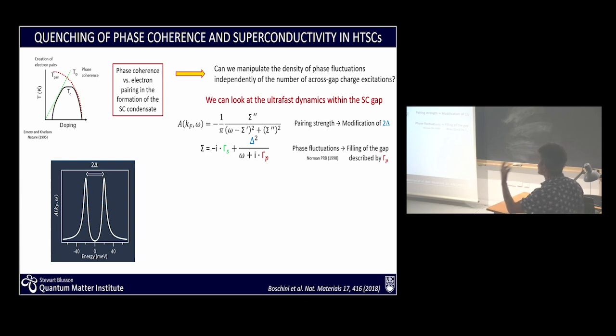If we go and pump the system and quench superconductivity, and we observe, for instance, that the gap gets smaller, then we know that by quenching superconductivity, or by pumping the system, we are quenching superconductivity through a reduction of the gap. If, however, we see that the peaks remain about the same position, and in fact they get broader, and spectral weight fills in the gap, then we know that we're quenching superconductivity by manipulating the gamma p, the pair-breaking scattering rate. So the idea is to do an experiment where we pump the system and see where the action is. Is the gap closing or is it filling? And we do it dynamically, and we use that as a way to define where much of the action is, either in the delta or in the gamma p.